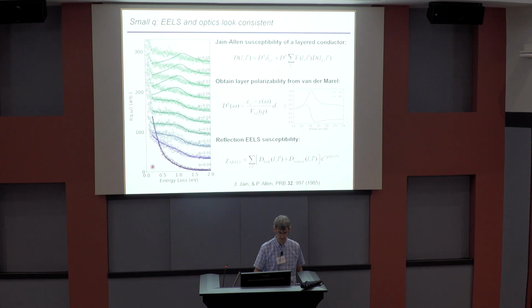What's shown on the left are a set of EELS spectra. The points are the actual data. I'll tell you what the lines are in a second. And these are done for a series of momenta. This is an energy from 0 to 2 eV, so the plasma frequency is at around 1. And then these are different momenta measured in reciprocal lattice units. If you take 1 over this number, that gives you the wavelength of the excitation in lattice parameters. So this is 100 lattice parameters, this is 10 lattice parameters, and so on.